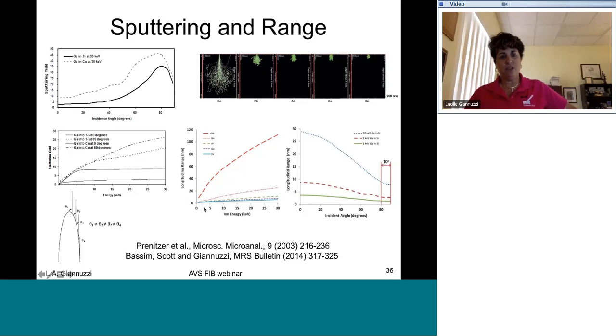The fact that we know this, that the range decreases as a function of ion energy, we're going to apply to our low energy polishing so that we can make really pristine surfaces for improved EBSD and sample prep, particularly for TEM sample prep. And we also see that the range decreases as a function of incident angle.